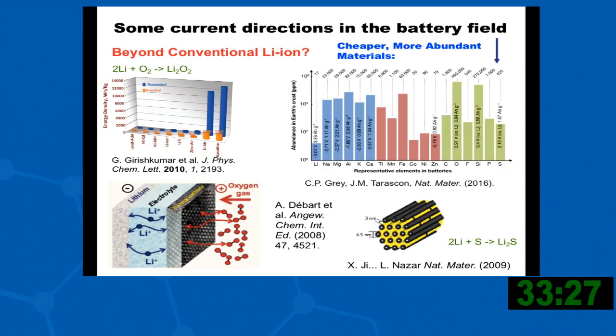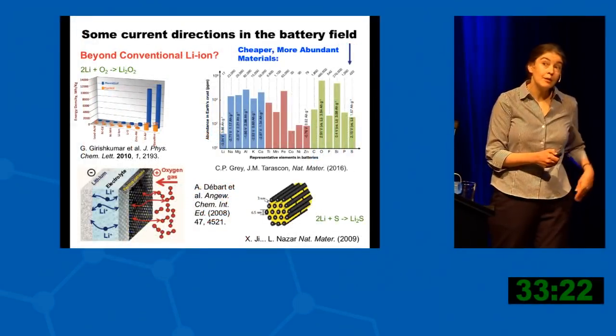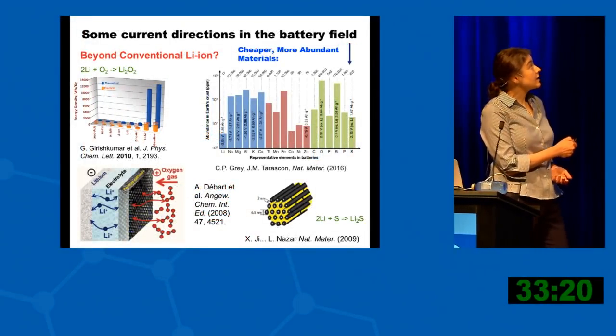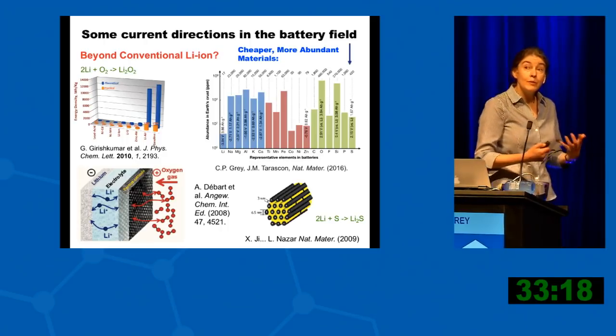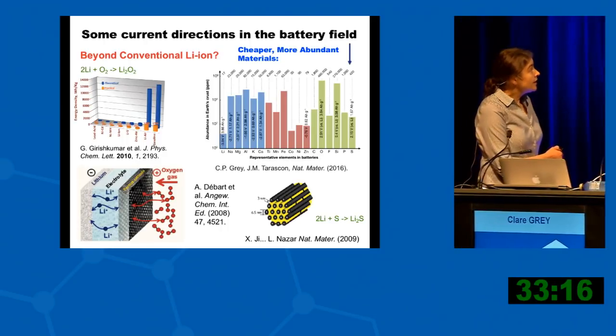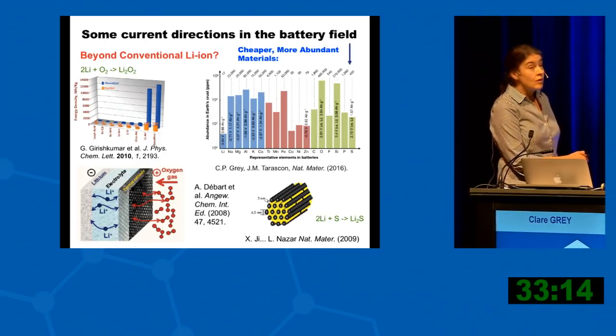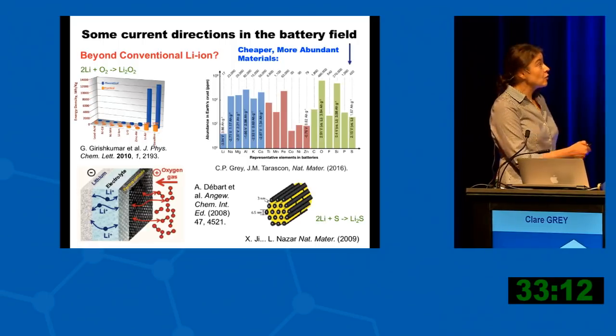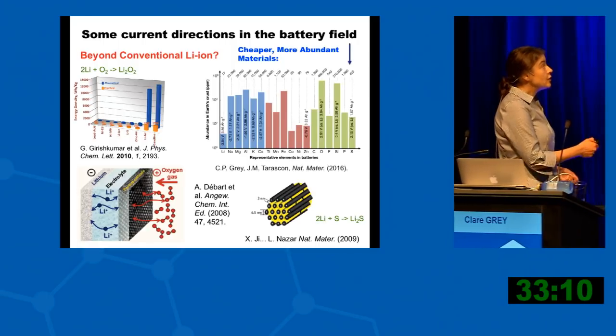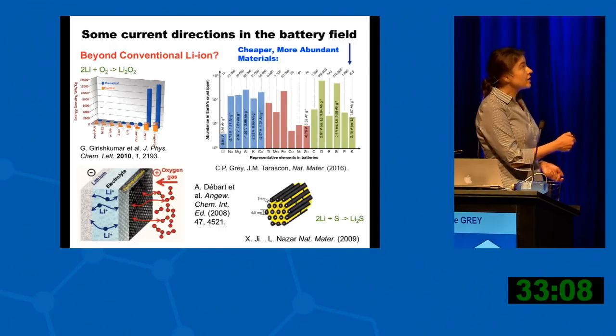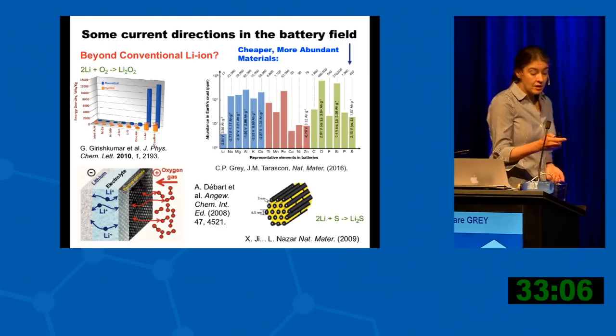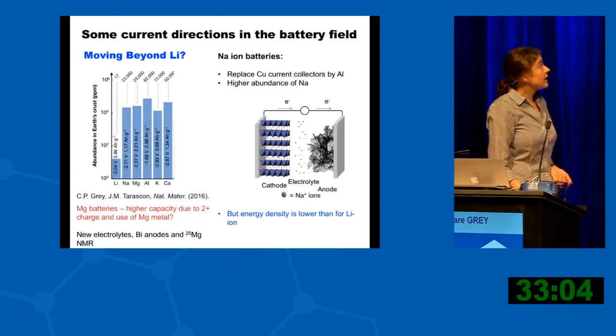The ultimate battery is the so-called lithium-air battery, where lithium reacts with oxygen to form peroxide. Why it's the ultimate battery is that it has the energy density of gasoline, both theoretically and practically. If you could get that to work, it would be transformational. The challenge is that it has all of the problems of a battery and all of the problems of a fuel cell, because you take oxygen and put it in a porous electrode to make a solid material. I'll touch on that later.